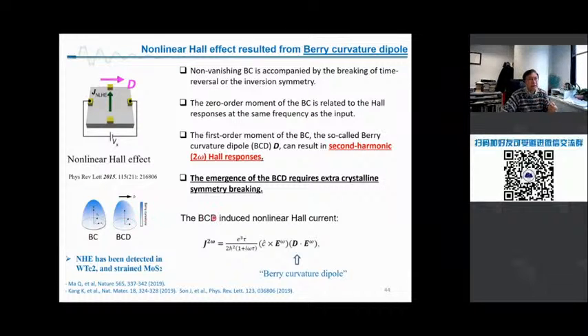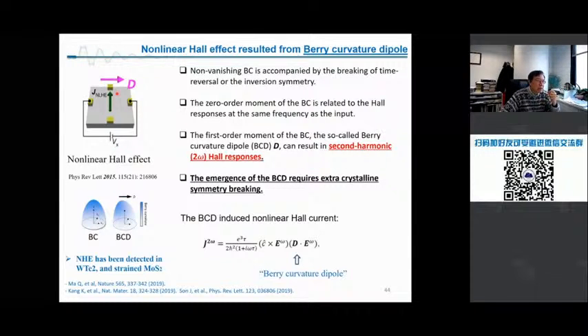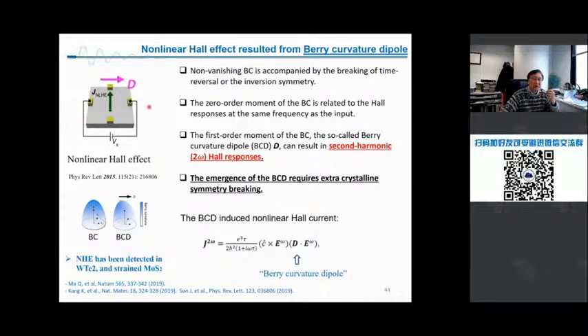This is a dipole vector, and this results in a second harmonic Hall response. I mean, once I use a frequency omega and I measure in perpendicular directions at 2 omega, you detect a very strong signal. That's exciting. And theoretically, people can use this formula. This is the electric field and the Berry curvature dipole terms, and they will generate the second harmonic signal.